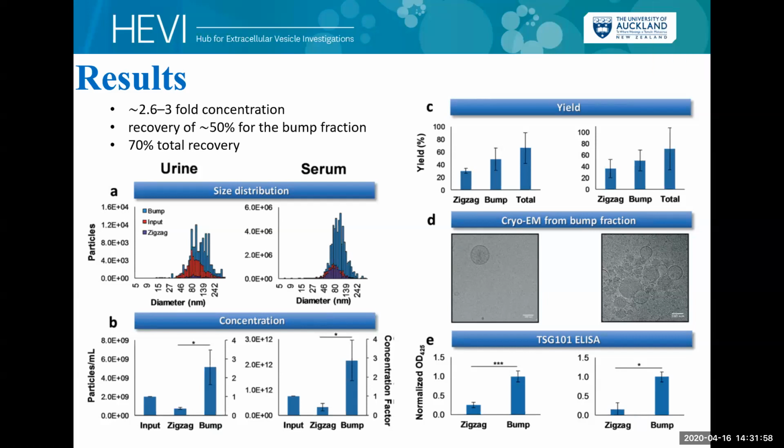Right, right. I think the thing that they might want to look into is figuring out proper surface chemistry functionalization to prevent the sticking in the first place. From what I remember, they purged it with BSA, and that's all they tried, but there are a lot of commercially available self-assembled monolayers that you can coat chips with to prevent cells and other things from sticking. So maybe they'll try that in the future, I would hope.